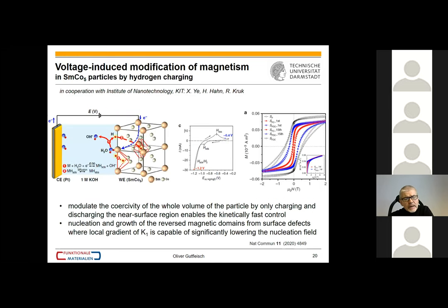Okay, now I stay with samarium cobalt, but this is now the 1-5 system. And here in a cooperation with KIT Karlsruhe, the idea was that we have a voltage controlled charging and discharging of samarium cobalt 5 with hydrogen. Basically, we have a magnetoelectric tuning of magnetism. And this was shown on very thin films, but here we can extend it to several hundreds of microns and almost, let's say, becoming a bulk.